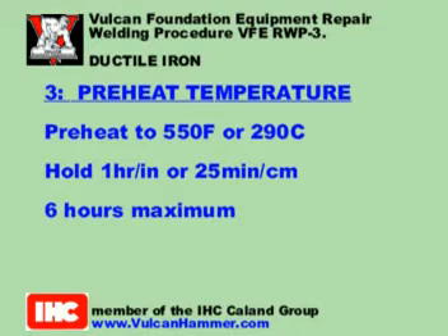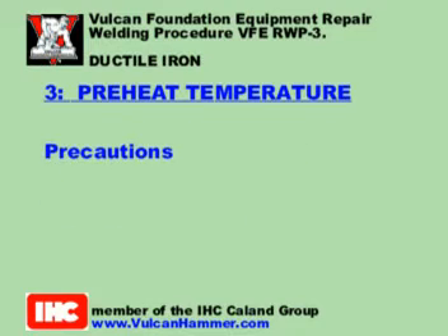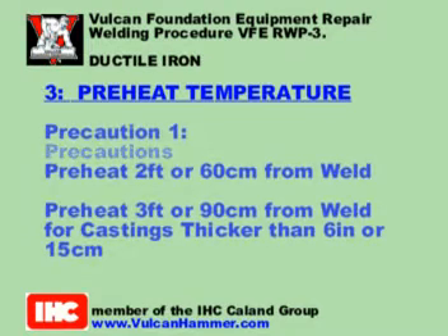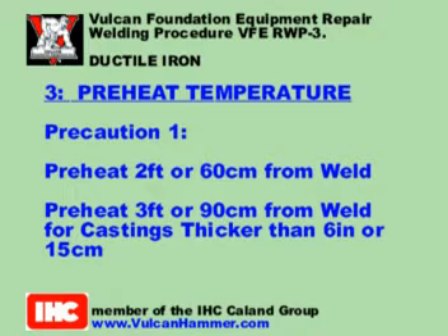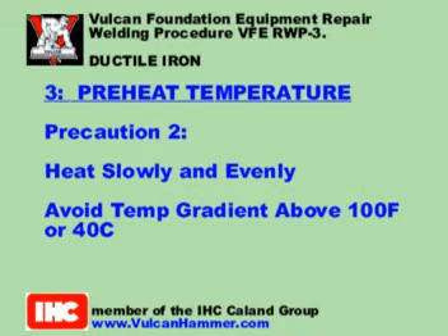Localized preheating may be used when furnaces are not available. The following precautions should be observed. Item 1. The area preheated must be at least 2 feet or 60 centimeters from the edge of the weld cavity. Castings more than 6 inches or 15 centimeters thick should be preheated at least 3 feet or 90 centimeters from the cavity.